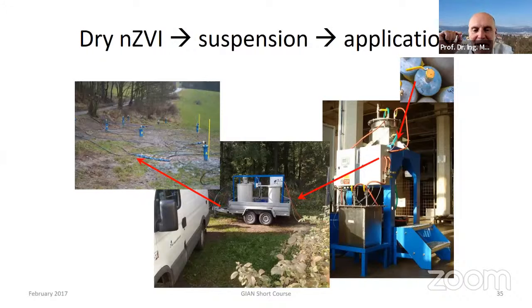And then you make the final concentration, which is about 1 gram per liter, relatively low, and you pump such suspension into a few injection wells, which are on the picture here. These wells are about 25 meters deep, and you are able to inject the particles there and apply them for treatment of contaminated groundwater.